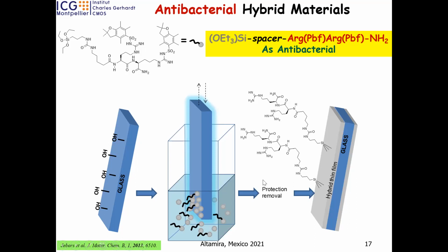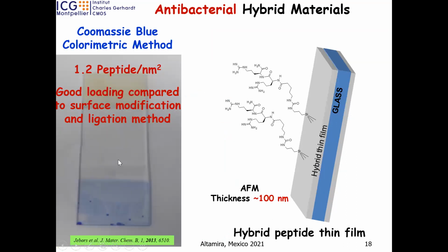And after that, deprotection can be done by thermal treatment or by TFA, trifluoroacetic acid, sorry. And you get your substrate modified with a thin film, mainly silica, and sometimes you have your peptide on the surface. The thickness is here around 100 nanometers.